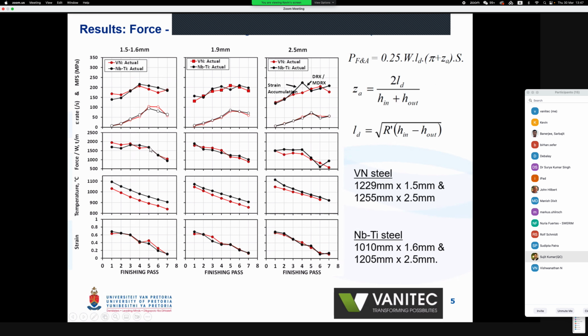The roll forces per unit width were also pretty comparable. But what is interesting here is that they were comparable despite the fact that the rolling temperature of the vanadium steels was comfortably below that of the niobium titanium. And this is also for a constant rolling schedule in the finishing train. The other exciting thing was that we could roll the vanadium steels wider.